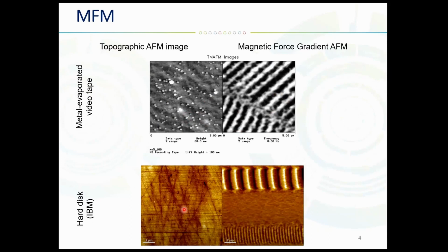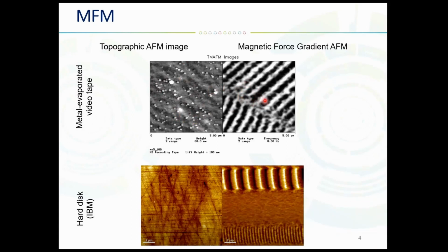Here on the left-hand side is a topographic image of the hard drive, and not surprisingly, you don't see many features here. And on the right-hand side, at a certain lift-off distance, when the frequency shift is plotted, you can actually see very clearly the bit patterns that are written on the hard disk media. The same situation is in metal evaporated videotape. On the left-hand side, you can see a topographic image with the metal particles on the surface of the tape. And here you do not see any pattern at all. But on the right-hand side, when you use magnetic force AFM, you can see basically the magnetic fields and the information that is written on this tape.